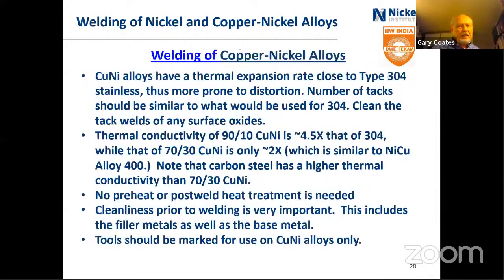I'm now going to move on to the copper nickel alloys, because that was specifically requested, and they are somewhat different than even the nickel copper alloy, the Monel 400. The copper nickel alloys have a thermal expansion rate closer to 304, so they're higher than most of the nickel alloys, and therefore they're more prone to distortion than the nickel alloys. So you want to keep the number of tacks to keep it straight, should be what you might use on a 304 material. And of course, it's very important to clean the tack welds of any surface oxide or any other contamination after you have done the tacking.